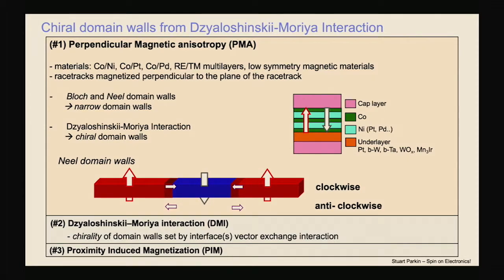This is just shown in this cartoon. If we take a layer of cobalt, for example, on the atomic scale and place it on a layer of a heavy metal like platinum, tungsten, tantalum, then that interface gives rise to a chiral vector interaction that causes the domain walls in a perpendicularly magnetized film to be either clockwise or anti-clockwise in their nature, to be Néel domain walls in which the magnetization, as you can see in this cartoon, rotates from an up to a down direction by rotating in a plane perpendicular to the domain wall, as opposed to a Bloch domain wall where the magnetization would rotate within the wall itself. That's favored by dipole interactions.